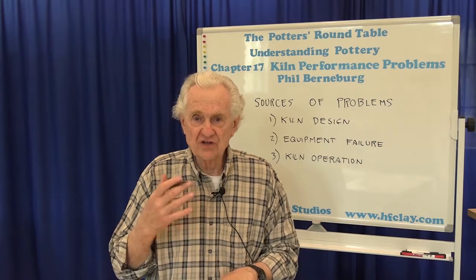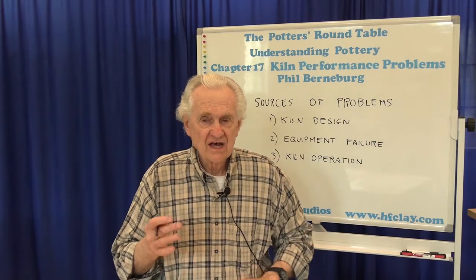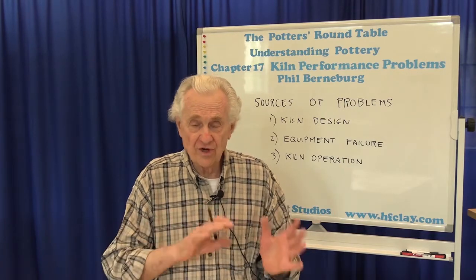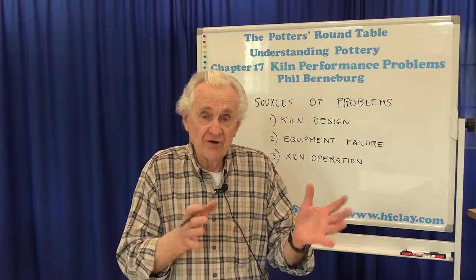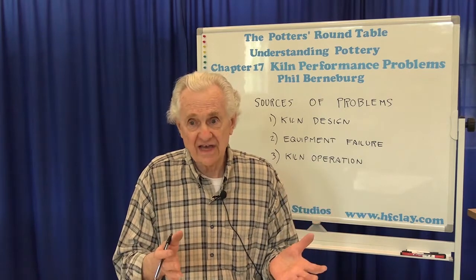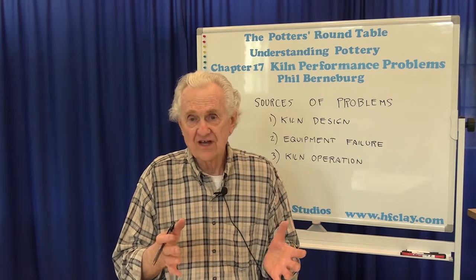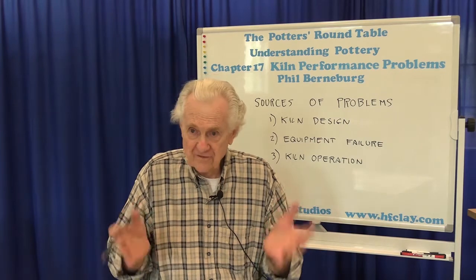Unwanted soot formation. If you're trying to get reduction in a gas-fired kiln, unless you're purposely trying to produce carbon trapping for, let's say, a carbon trap Chino glaze, you don't want to produce soot. When you see soot being produced, it means you're getting into too heavy reduction. The reduction is way too heavy. You want to produce carbon monoxide, which you can't see. You don't want to produce soot. And so when you're producing soot, basically what it means is you're not burning the gas efficiently. You're wasting a lot of gas. And therefore, if you're wasting gas, you're not generating enough heat. And therefore, the temperature won't rise.